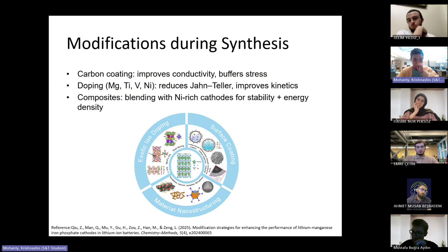But again, the key takeaway from all of this is each and every synthesis method has its own advantage. None of these synthesis methods can achieve everything that each synthesis method claims, and that creates a gap. If there was one synthesis method which could get nanosizing, scalability, reusability, or any standard that the battery powder could be made upon, we could have a simple synthesis method that each and everyone follows. But because there is no standard and each synthesis method has its own advantage, there is no go-to paper or synthesis method that we can just pull out and achieve the desired powder.